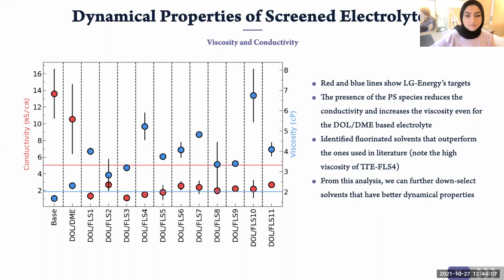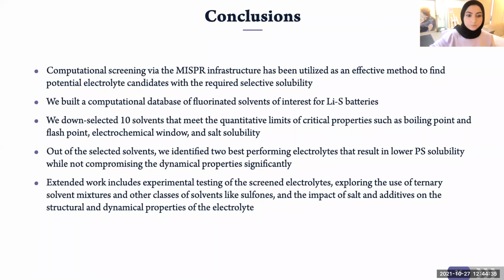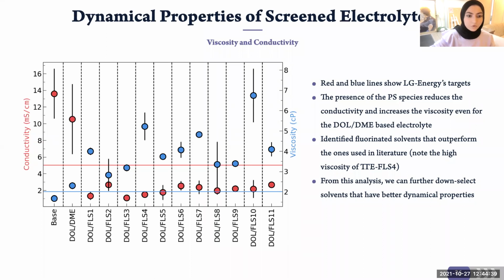But for the fluorinated solvents that we introduced here, we can see that there is a higher viscosity and lower conductivity in these electrolytes, which is also expected because of the lower solubility of the polysulfides and the formation of bigger clusters. But our objective is to achieve a compromise between the solubility of polysulfides and the dynamical properties. So if we look at FLS2 and we compare it to FLS4, which has been used in the literature, we see that it has much better dynamical properties while it is still achieving very low polysulfide solubility. So it can be one of the promising candidates for more detailed studies in the future.